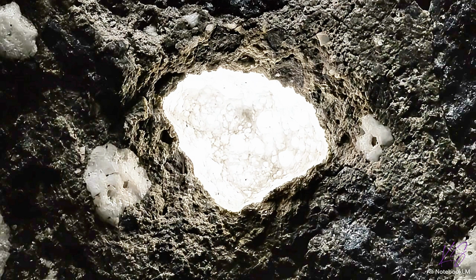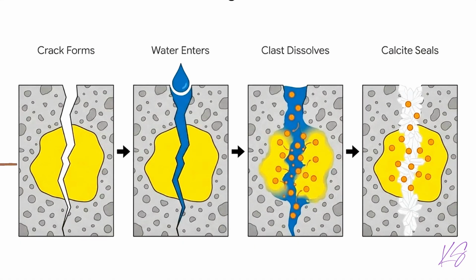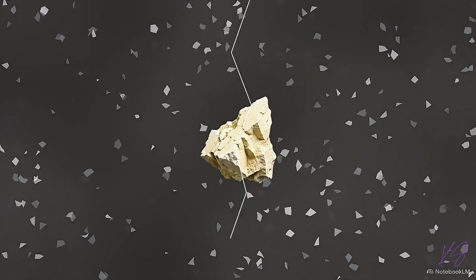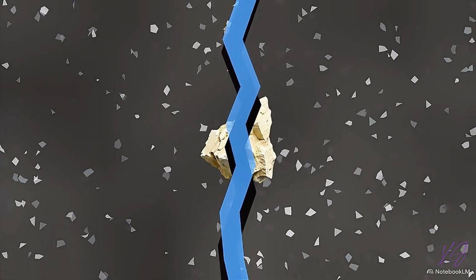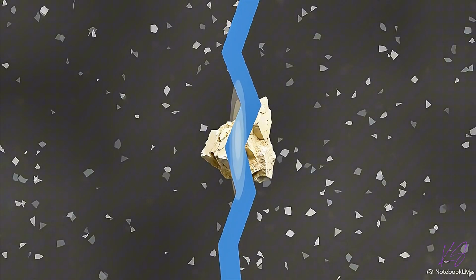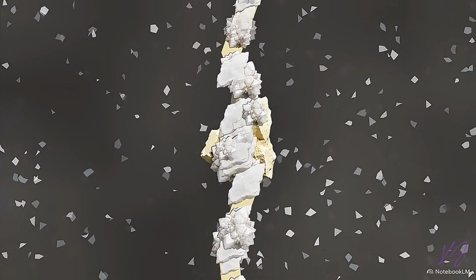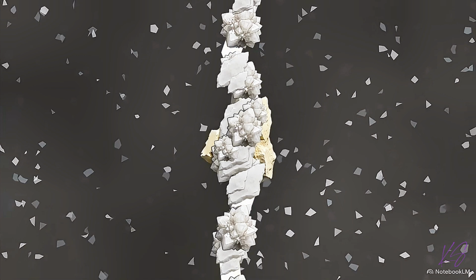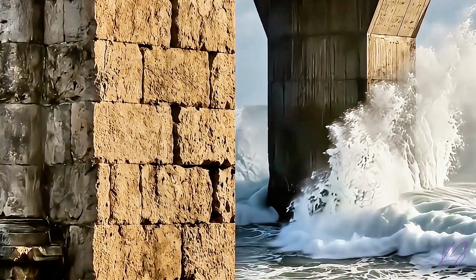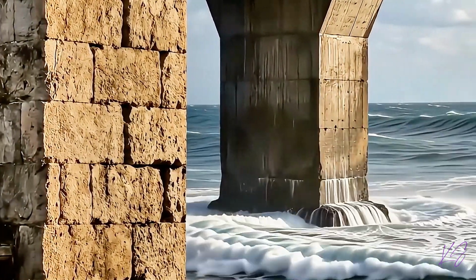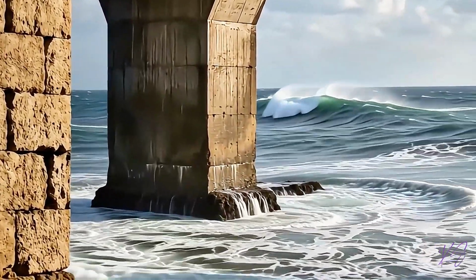concrete matrix. These calcium reserves, known as lime clasts, are the engine of a terrestrial self-healing mechanism. When earthquakes or ground settling cause microscopic cracks to form, they naturally propagate through these brittle clasts. As ambient moisture infiltrates the fracture, it reacts directly with the calcium core. The dissolved calcium saturates the fluid and spontaneously recrystallizes into calcite, sealing the void before the fracture can spread. On land, the concrete heals its own wounds. But in the ocean, it executes a completely different chemical survival strategy.